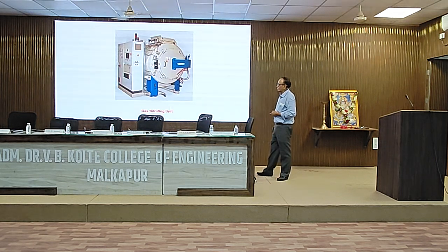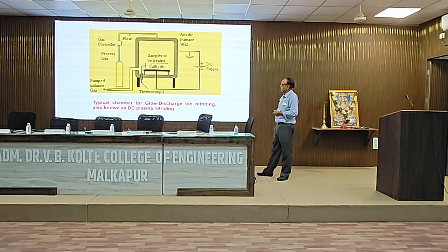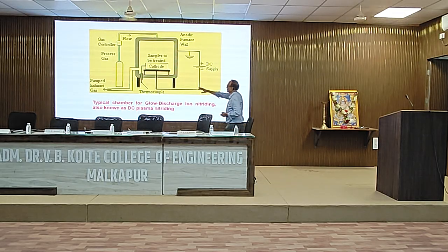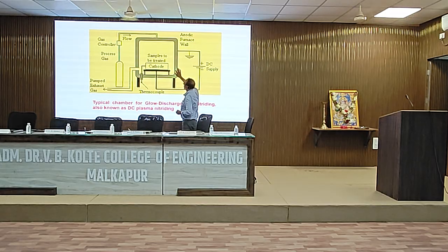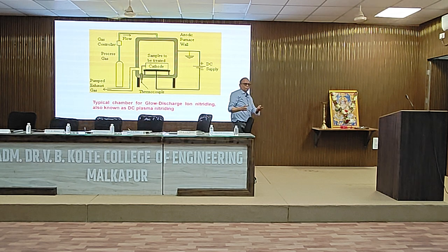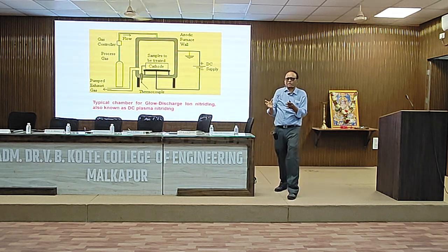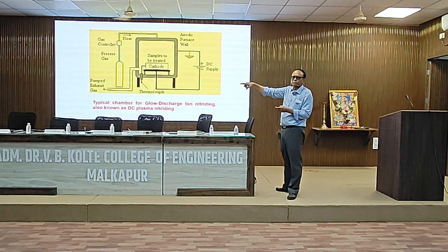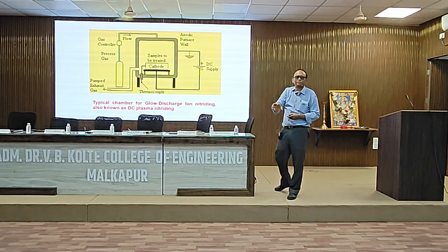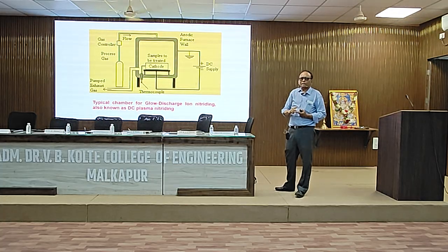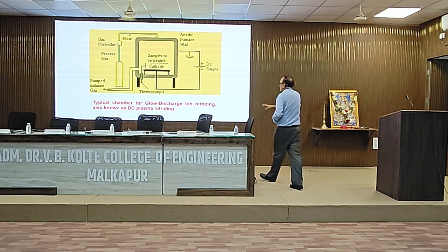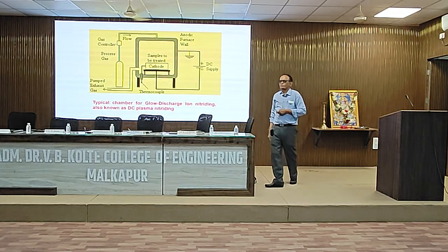Now, of course, there are a very large number of gas nitriding units. I have taken this from the literature again. Big size components are being nitrided for industrial use. Again, in glow discharge nitriding or plasma nitriding, you have the cathode, and the chamber is the anode, which is grounded. You apply the negative potential here, positive is grounded here. There is a gas filled, nitrogen and hydrogen, and because nitrogen and hydrogen are there, you generate the plasma containing nitrogen ions, hydrogen ions, and all these things. Hydrogen ions will remove the oxides on the steel, and you can have very precise nitriding of the components, and we can achieve a single phase nitride in the case of this component. And this process is now industrially well adapted.